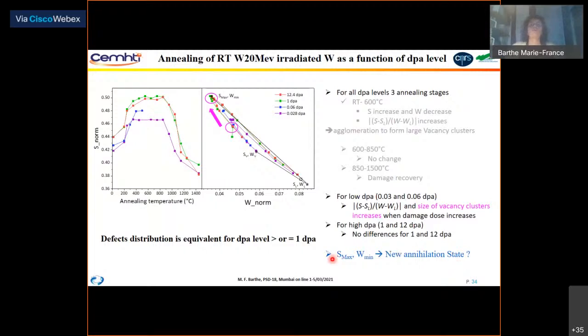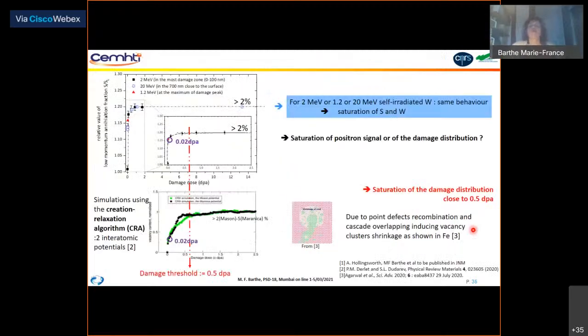And there is something interesting, which is also this point, S max W min, and we will ask if it is a new annihilation state. So we have this saturation of damage distribution, and we think that it is due to point defect recombination and also to the cascade overlapping, which induces vacancy cluster shrinkage, as it has been shown yesterday, if I remember correctly, by Farida, in iron, where the vacancy clusters, which are created by the first cascade, can be shrunk by the interstitials that are created by the second cascade. So we have this damage threshold of 0.5 dpa.